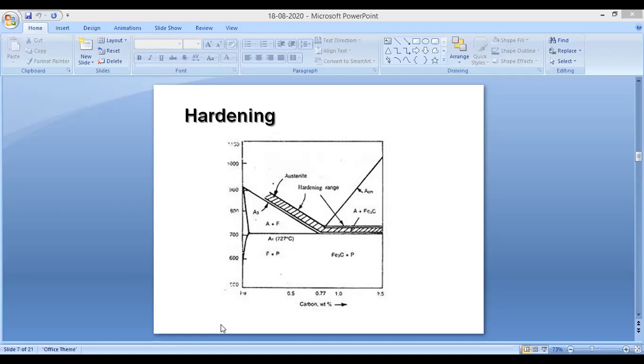Hardening is done of steels containing more than 0.3% carbon, as the gains in hardness are most sustainable in these steels. Mild steels, which contain less than 0.3% carbon, tend to be difficult to harden with not much increase of hardness because critical cooling rate is attained with difficulty, and that too in very thin sections by using drastic cooling, which may cause distortion and cracks.